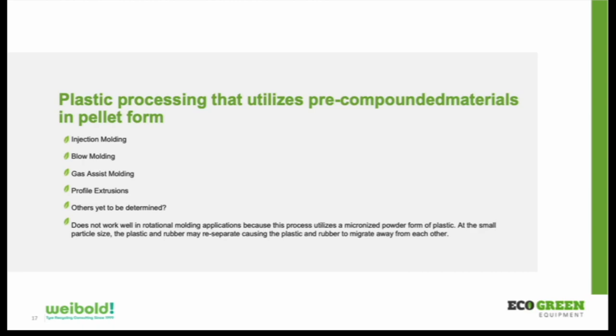And then what we would have shown in that same video is those pellets then we took to an injection molder in Michigan, and we were able to manufacture from that material handles for tin snips. They were able to put it directly into the machine. No changes in temperatures, no changes in their processing techniques at all. It was simply replacing the all plastic pellet that they had with a new plastic rubber pellet, and we were able to run that